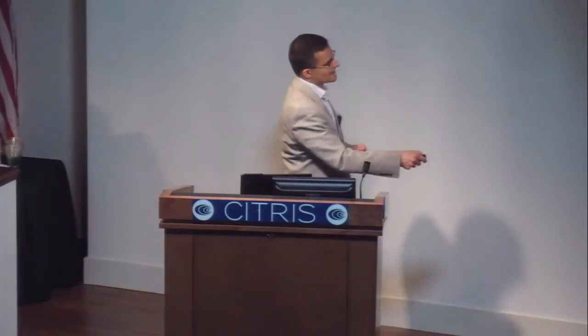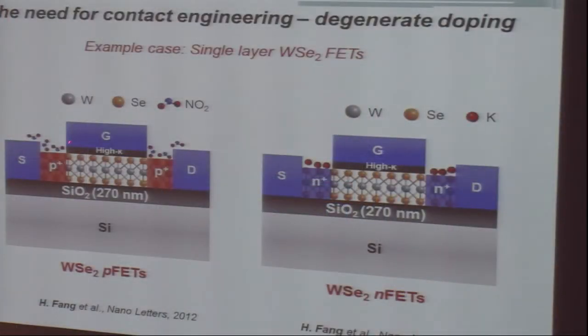What you do is put a molecule or a material on top that is either electron withdrawing or electron donating. You play around with the HOMO and LUMO levels of your molecule, or similarly the conduction band and valence band edge positions of your molecule and the material. By choosing the right combination, you can either withdraw electrons or donate electrons.